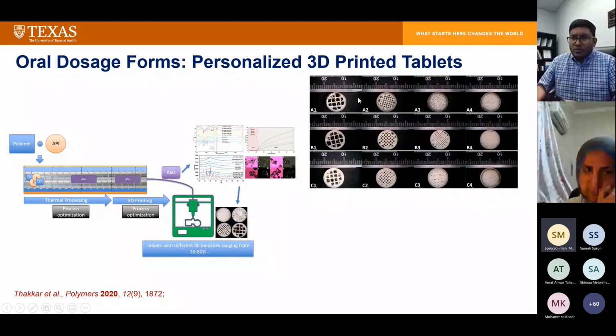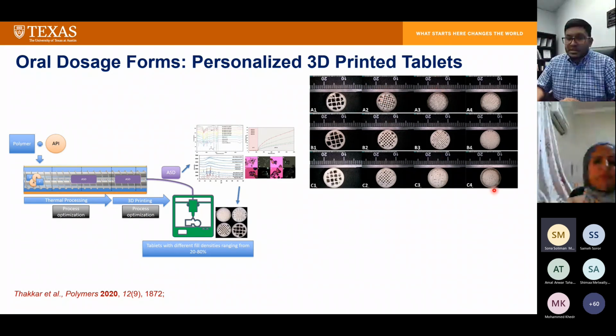So in this photograph over here, the left column is basically with 20% fill density. That means we are only filling 20% of the whole surface, whereas the second one is 40%. So that means we are actually filling 40% of the whole surface. The third one is 60%, and the last one is 80%. So as you can see, the higher the fill density value, the denser the tablets, right?